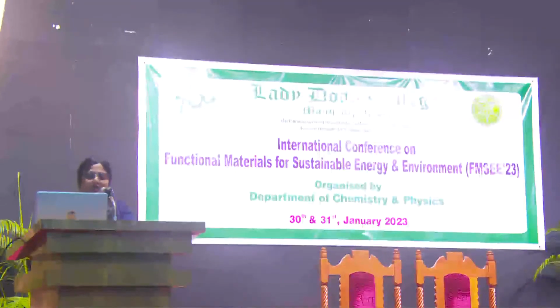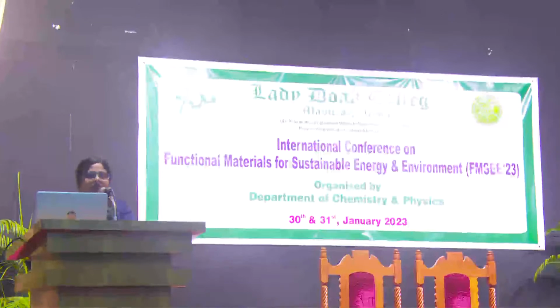Other applications such as supercapacitors, dye degradation and heavy metal removal can also be done. We have explored supercapacitors and dye degradation in detail in other papers that we have published. The supercapacitive behavior is very good because of the high specific capacitance, as I mentioned, and it is also seen to degrade dyes such as methylene blue, via the several UV studies that we conducted.